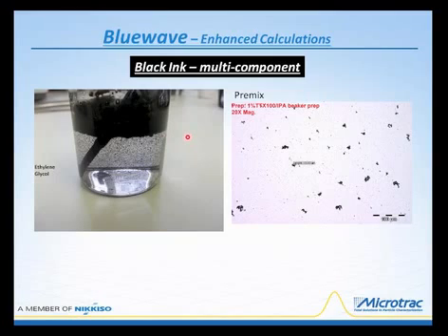Well, as we follow through our laboratory SOPs, one of the first things we do is test the material to find out if it's going to wet out and mix well with any particular suspending fluid. And what we find is that as we take this black ink and put it into ethylene glycol, the ink sticks to the pipette. It tends to float. There's some attempt for it to mix with the fluid, but this photograph doesn't show it, but these particles are actually trying to escape. They're starting to float towards the surface and trying to escape the ethylene glycol. That immediately told us trying to make this measurement in ethylene glycol was not going to work.